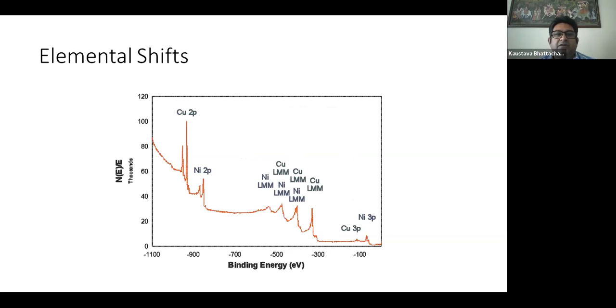Okay, so now the elemental shifts. Now we check, for the copper 2p and the nickel 2p, we have a definite shift. You can see that for copper and nickel, as the elements are different, the binding energies of these peaks are also completely different. And usually, the binding energy of the electron in this regime, for copper 2p, and the equivalent for nickel, is coming to a higher binding energy.